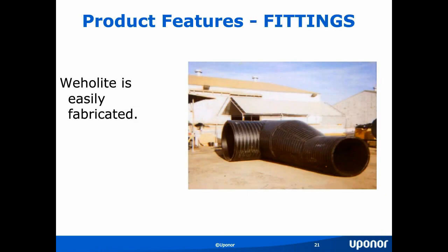Both our facilities in Huntsville, Ontario, and Saskatoon, Saskatchewan have fitting shops. And they can manufacture and fabricate pretty much any fitting that you require in order to complete your project. So what you're looking at here is 60-inch diameter Weholite bending through an elbow at 90 degrees and then being reduced down to 36 inches and going on from there. That particular fitting is likely going into a foul air system in a municipality, but we can make any type of fitting for any type of application that you need.